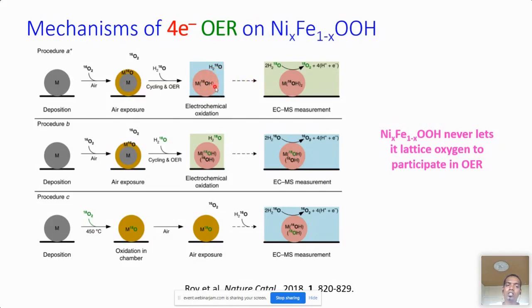But when they took this catalytic material having only oxygen-16 isotope, and ran OER with water molecules containing only O18 isotope, they found that the evolved oxygen contains only O18, which means that the oxygen within the lattice is not participating in the oxygen evolution reaction with this material.